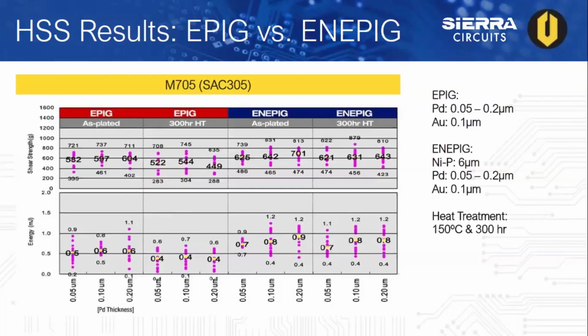Now here we have high-speed shear results for EPIG and ENEPIG, a comparison. The right-hand side shows the thicknesses that were tested. The conditions during testing involved using SAC 305 solder with as-plated boards, and also boards that went through a heat treatment for 300 hours at 150 degrees Celsius. ENEPIG resulted in higher reliability compared to EPIG when looking at the shear strength results.